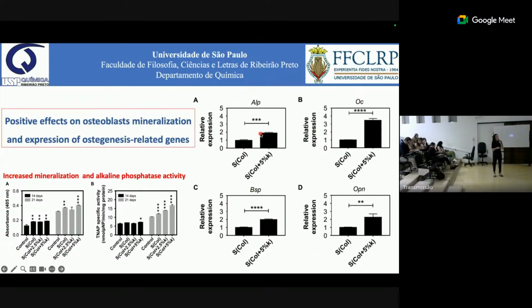In the presence of carrageenan, here called plus 5% kappa, we also increased the expression of the main genes related to the differentiation of pre-osteoblasts into a mineralizing phenotype: alkaline phosphatase, osteocalcin, osteopontin, bone sialoprotein. So our hypothesis, that the substitution or the addition of a material similar to a glycosaminoglycan could enhance the performance of osteoblasts, was confirmed.